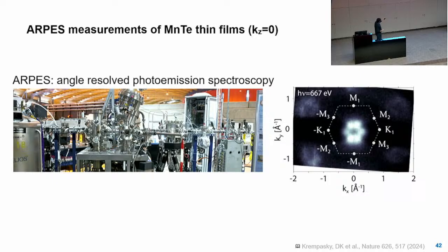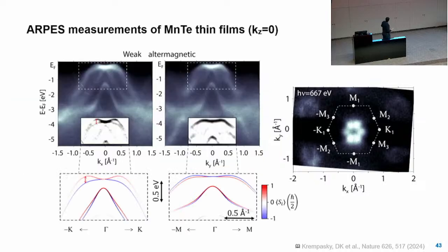So that's one of the pictures you get. You see again the hexagonal symmetry, but this is for one energy. Now we look here only at two dispersion directions, kx, ky. So what we are interested in is to look at kx versus energy, for example. And that's what we do here. We have here a map of kx versus energy, and you see these bands. This is how it's measured, let's say. And this is after a bit of what I call massaging of data, which you have to be very good at nowadays to visualize exactly what is there to be seen.